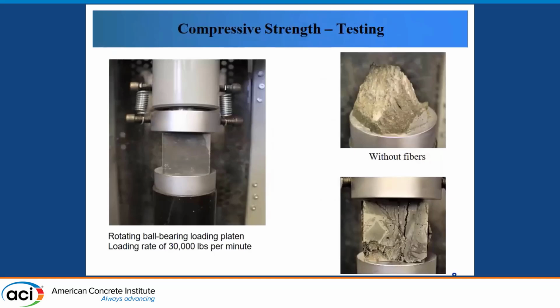Rotating ball bearing loading platens were used for testing the cubes in compression at a loading rate of 30,000 pounds per minute. Tests usually run from 2.5 minutes to 4 minutes. Without fiber reinforcement, the cubes failed explosively. The addition of sufficient steel fibers changed the failure mode from brittle to ductile, as you can see in the picture to the right side of the slide.